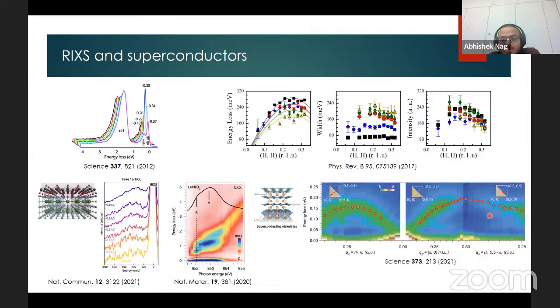And just this week, you may have seen three articles posted on arXiv demonstrating the presence of charge ordering in these systems using RIXS. Now, I should mention one thing: these magnetic excitations, the degree of nickel rare earth hybridization and the charge ordering largely depend on the presence or absence of the capping layer that is used to protect the sample, although this does not affect the superconducting properties. So in the coming years, we'll see the story of nickelate superconductors unfold, and definitely RIXS will contribute heavily to the experimental side.